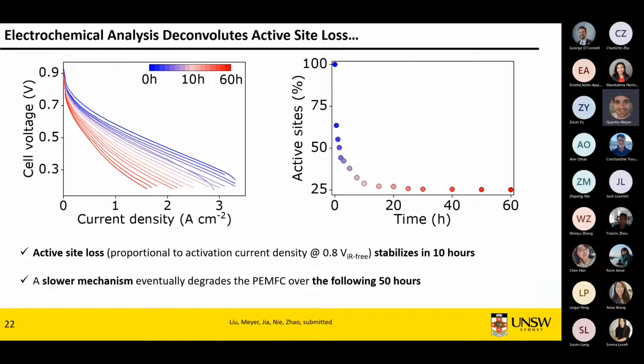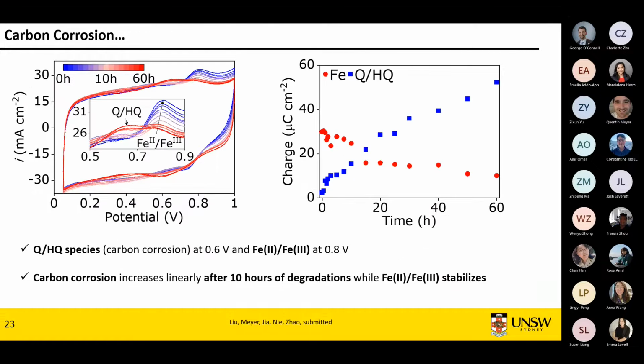Initially, you have 100% electrochemically active sites, and then within about 10 hours, you lose 75% of your active sites. That's quite bad. That's not what you want to see, losing that much active site so quickly. The interesting thing, however, is that in this region, which is about the next 50 hours, you don't really seem to lose active sites, but you still lose about 50% of your performance. So what kind of thing is going on here? What's very likely to happen is carbon corrosion.